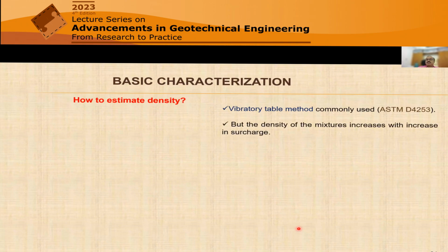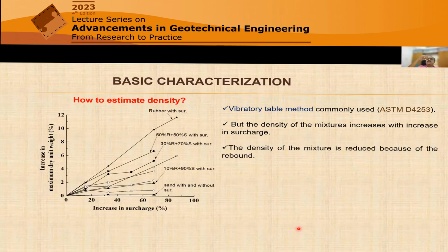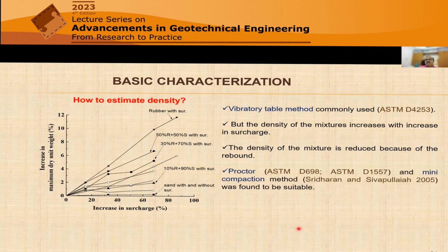The first problem we encountered is how to estimate the density, obviously. Because the regular vibratory table, which ASTM is suggesting, is not working, because the density of the mixture increases with increase in surcharge. Not only that, if you remove the surcharge at the end, the density immediately reduces because it tries to dilate out. I mean, volume expansion happens. So what is the best method? That is the first question. So we tried Proctor and then we tried a mini Proctor. In fact, the mini compaction proposed by Sridharan way back in 2005, a classic geotechnical paper, seems kind of ideal.